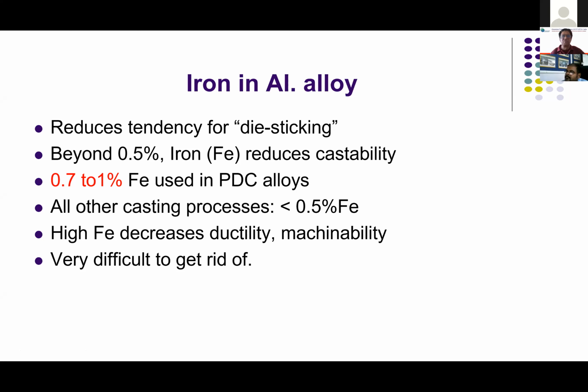Right? In many alloys where you require a higher elongation percentage, try to reduce the iron even below 0.2. Normally we recommend below 0.4 for the commercial grade castings in GDC and LPDC. The problem comes in PDC, where the dies are steel dies, and you all know that aluminum alloy has a very great affinity, a liking for the steel. Therefore, it tends to stick, चिपक जाता है.